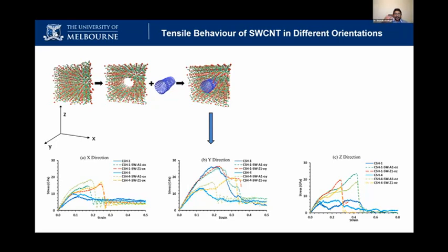What is happening when we are coming from bottom to top, from nano to mesoscale, is that due to the defects and the porosity, the two main reasons, the strength reduces by 10,000 times. So if we can find how to further avoid the nanoscale voids, the impurities or the defects, we can harness the potential of the concrete. For example, as I mentioned in the beginning, the concrete can go up to 800 megapascal using this special treatment method.